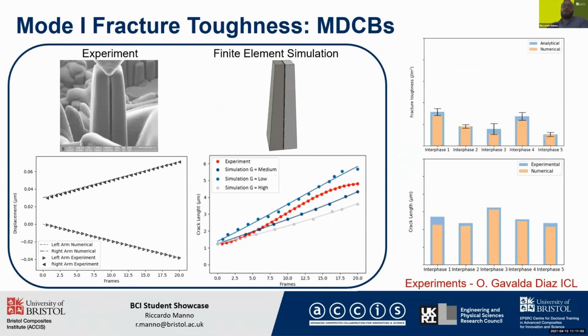So furthermore, the quantification of properties like fracture toughness and frictional shear stresses happening at this scale was necessary to conclude the topic about the interface material. Hence, with the materials group of Imperial College London, we developed a virtual experimental capability which allows the calculation of these quantities. Particularly, we developed this microcantilever beam test for mode 1 fracture toughness, where we used a cohesive layer to enforce the interfacial behavior between fiber and interface material.